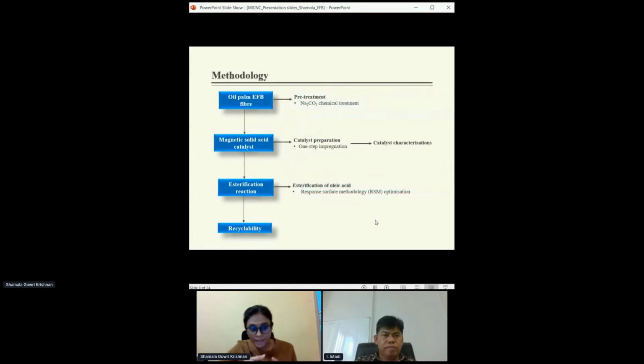To execute our aim, here is a brief flow of methodology: from the oil palm EFB fiber chemical pre-treatment using sodium carbonate, and the treated fiber will be used in magnetic acid catalyst preparation by one-step impregnation method, and its utilization in esterification reaction to study its effect on the catalytic reaction parameters by Box-Behnken optimization design, and finally to examine the catalyst recyclability.